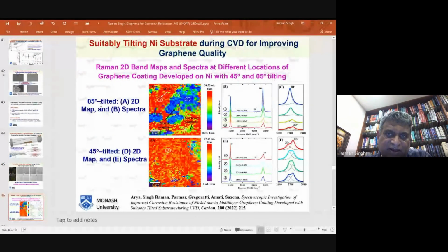Again, we did Raman spectroscopy, and we could show that if you have a 5-degree tilted sample, the graphene is not uniform, and you will appreciate it more when I take you to the 45-degree tilted sample. On the entire surface, graphene coating is uniform, as we could show by Raman spectroscopy. You can see that Raman results are the same for all the points, whereas Raman results are not consistent for different points if you have 5-degree tilting.